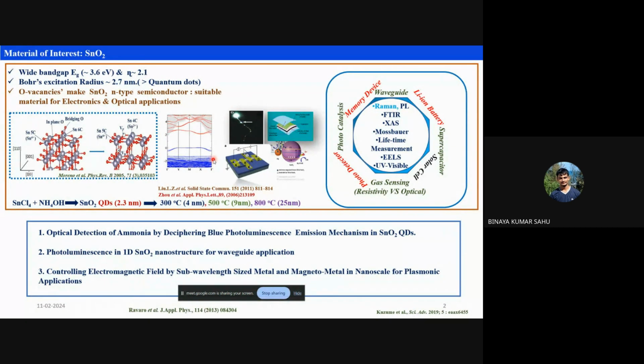But whenever there is some kind of defect, especially oxygen vacancy, what is that oxygen vacancy? Here we can see the structure of tin oxide. Generally in tin oxide, it consists of tin and oxygen, and one tin is surrounded by six different oxygen, and their positions are very much fixed.